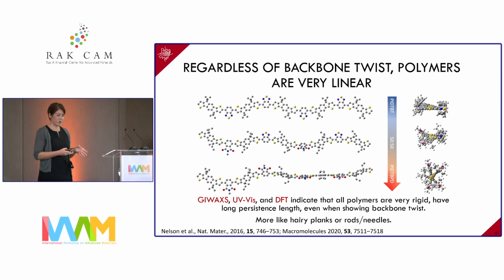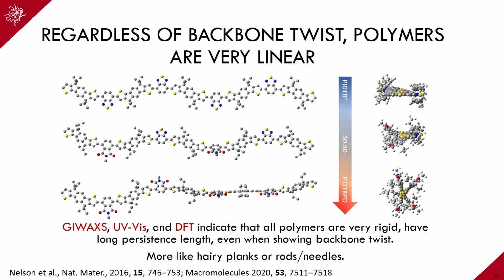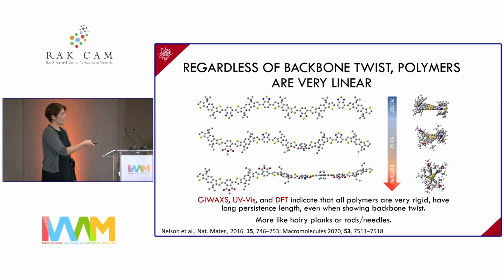So I'm not going to go into the detail of all the characterization that we did, but ultimately, through a variety of characterizations, including GIWAXS, UV-Vis, and additional DFT calculations that we performed, what became clear was that the cartoon diagrams that we draw just are not true. And in particular, these IDT monomers, because you have this very planarized monomer with hairy side chains coming off, the more accurate description of these is really hairy planks or rods. So regardless of the twist that we have in the polymer backbone, in the squishy one, you have a hairy needle-like structure.